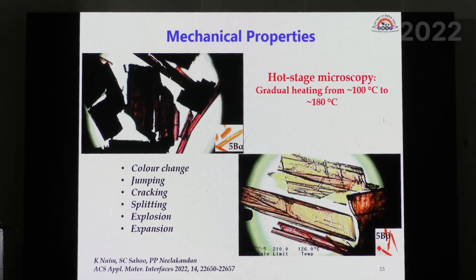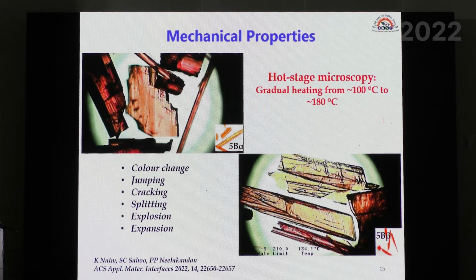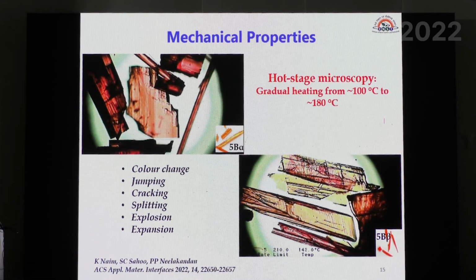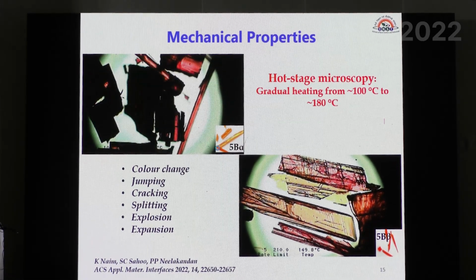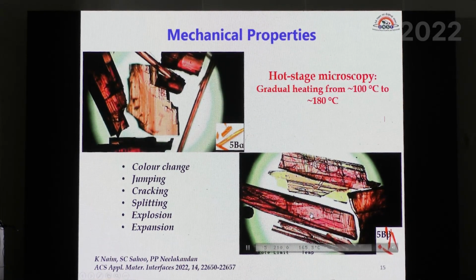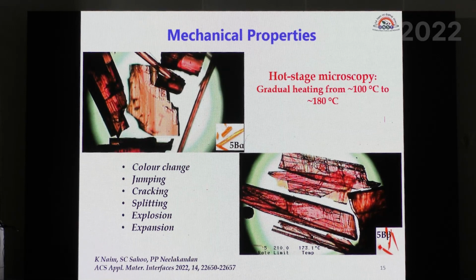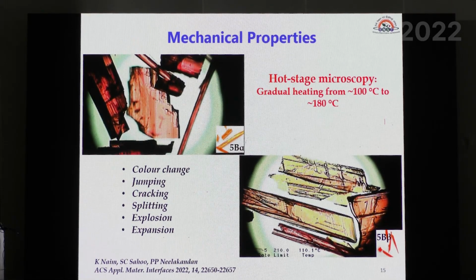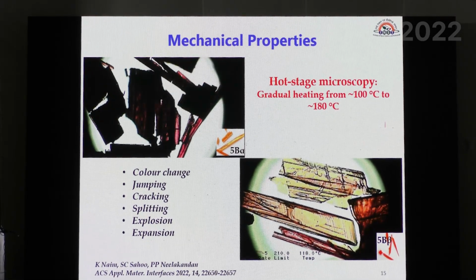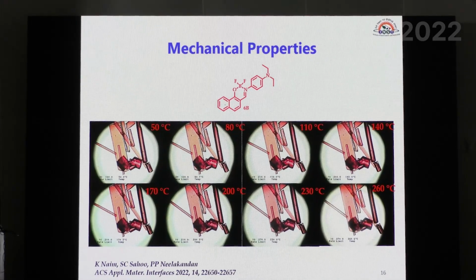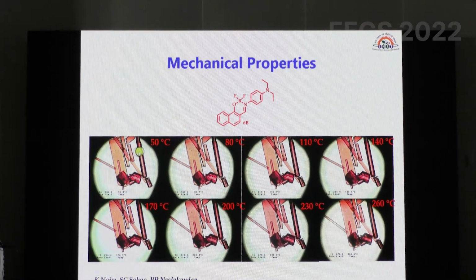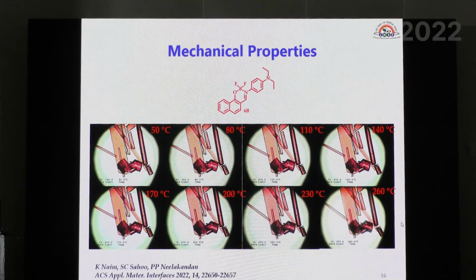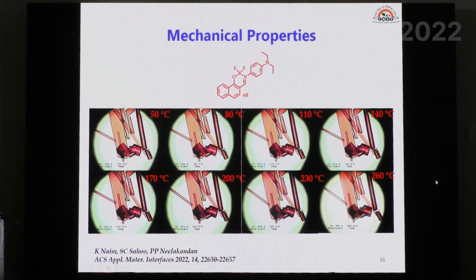Color change will be there. Some of the crystals move away from the focus of the microscope. Some of them crack, some of them split, and then expansion, explosion, all these properties we see. In the case of the other polymorph, we don't see all these properties, but mostly color change and a little bit of movement. And if you look at the other isomer of the same compound, nothing happens. If you heat it from 50 degrees to 260 degrees, nothing happens. It remains exactly the same.